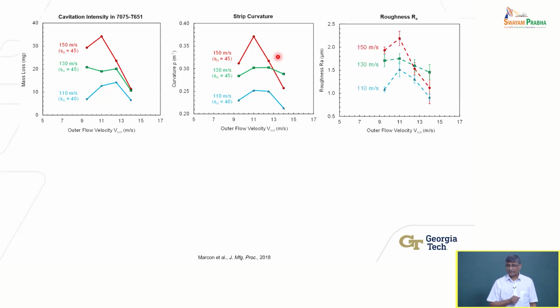What happens to the roughness? Roughness is bad. Too much roughness is bad. So while I will generate more residual stresses, I'm also roughening the surface because these vapor bubbles are collapsing and deforming the material plastically. So what happens if you take a marble that you all have played with at some point and take a soft metal and throw it at it, you'll produce an indentation. But if you zoom in on that indentation, material will have plastically deformed on the sides, right? It'll produce a ridge, material flow.